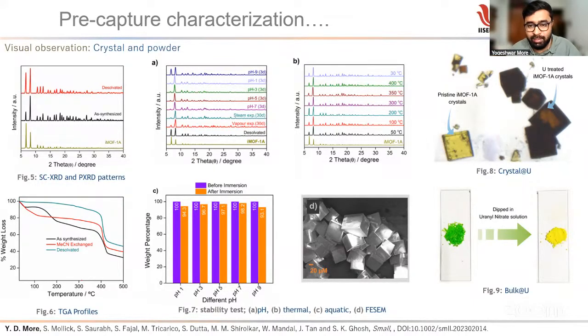We should go for the PXRD. So we did the temperature dependent PXRD, where the temperature will go up and we'll see what is the change in the crystallinity. Here you can see the structure is written. From 30 degrees, that is nearly room temperature, we went up to 50, 100, 200, 300, 350, 400 degrees in a controlled atmosphere, and we again came back to 30 degrees. What we observed, the crystallinity is maintained as it is, so the given MOF is at least stable up to 400 degrees centigrade.